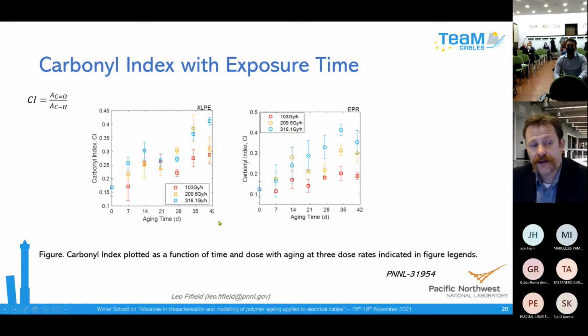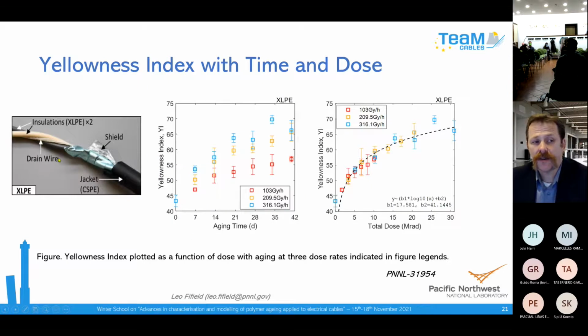We measured carbonyl index. This is a Fourier transform infrared spectroscopy technique to look at the formation of carbon-oxygen bonds on the surface of the polymers. We saw a trend with dose. For one of the insulations we measured, the XLPE was a white-colored insulation. An area that we've developed in the last few years that's been fruitful is quantifying color change. It works better for light color materials than dark color materials, but color change actually tracks pretty well with polymer aging. So we measured the color change of this insulation with exposure, and it's a very surface sensitive technique, and we saw a dose dependence. It wasn't as linear as some of the others.